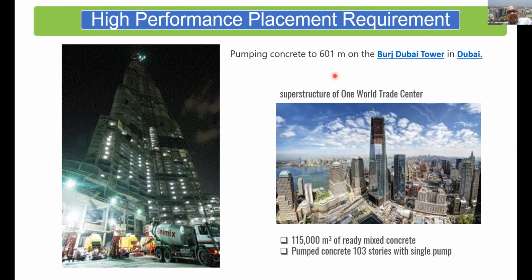This requires now understanding what happens to concrete when you pressurize it and how it flows in a pipe. And of course, it's an inhomogeneous suspension. You have aggregate, you have paste. You want to keep everything homogeneous so that once you pressurize it at one end, it comes out of the other end in the same state without showing any separation or segregation.